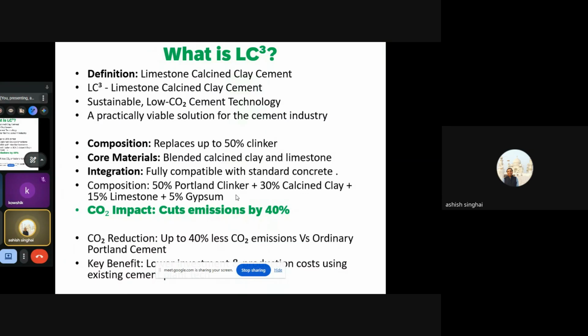Now, what are the core materials? Blended calcined clay and limestone. So blended calcined clay is in the raw form, and limestone in the raw form. We are not giving any temperature whatsoever. So this blend of clay and limestone is put to fine ground powder, and then it is given some amount of temperature to give calcination, but not to the extent of clinkerization. So that is how the composition takes place.